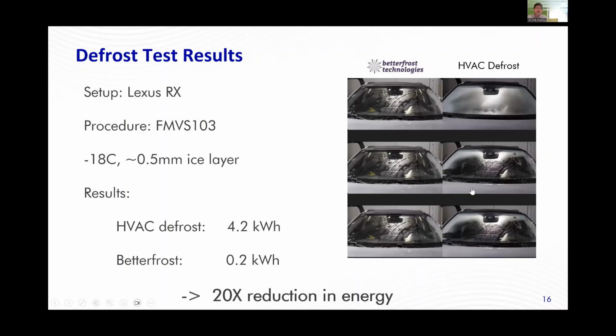And when we've done testing in the lab, this is FMVSS. We're using about 20 times less energy. It's compared to 4.2 kilowatt hours. We're typically using 0.2 and oftentimes in the low 0.1 range as well.